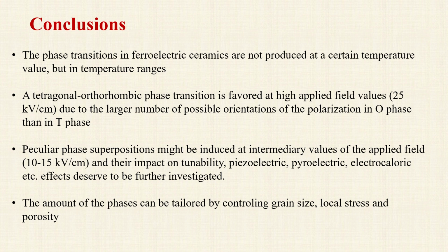The orthorhombic phase is very important because it presents 12 possible orientations, more than the tetragonal and rhombohedral phases. It is characterized by the highest polarization, which is a beneficial factor for increasing tunability, piezoelectric, pyroelectric, and functional properties in general. And another interesting fact shown in this work is that the maximum of the orthorhombic phase is not necessarily obtained at the highest applied field, but rather at intermediate field values. And this aspect deserves to be further investigated in poling experiments.